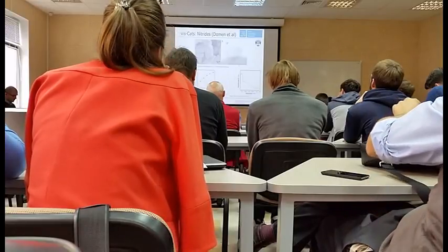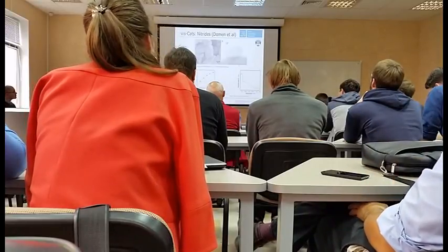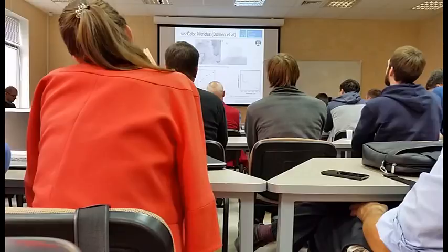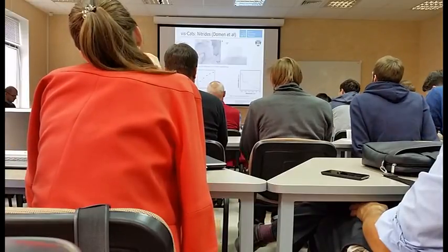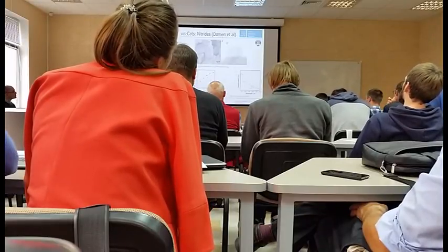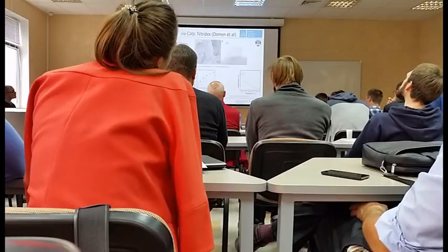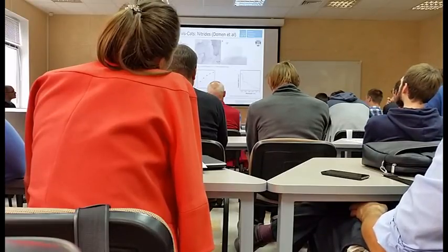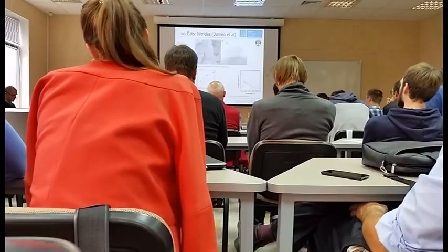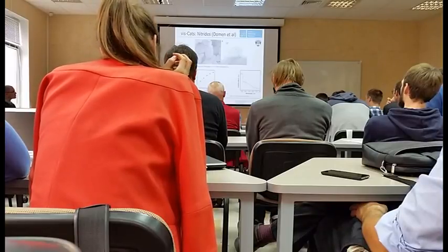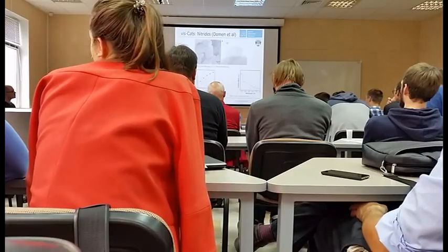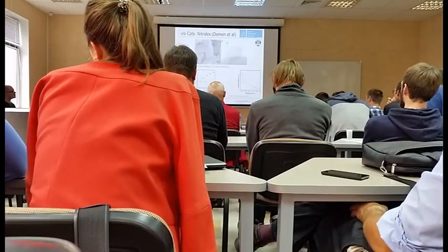These are some examples, again taken from the literature, of visible light photocatalysts from the very well-known laboratory of Professor Domen in Japan, and he showed that his systems were actually able to split water. However, even though this nitride system absorbed visible light nicely, as shown here, actually only the UV part was able to split the water, and the visible light one was a zero line here. No water splitting occurred there.